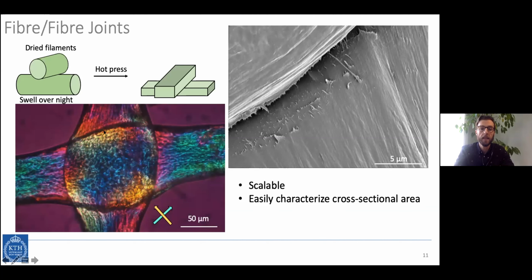Looking at the polarized optical microscopy here, we can see that within the joint the alignment changes during or following pressing. With the filament that is moving from right to left, we have a uniform alignment, but when it gets into the joint, we see changes in alignment of the cellulose fibrils. That allows us to understand what's actually happening within the joint.